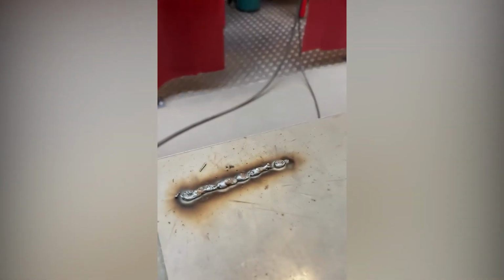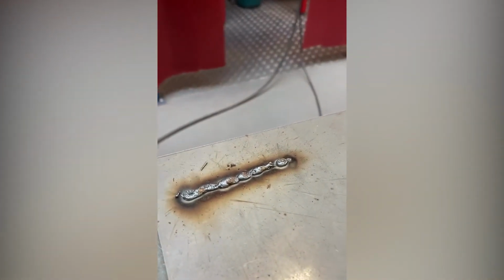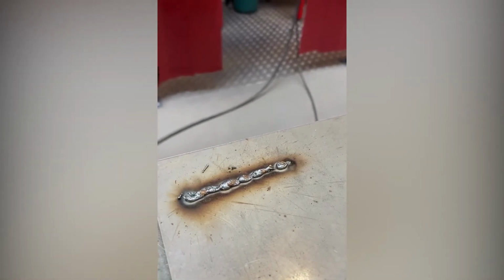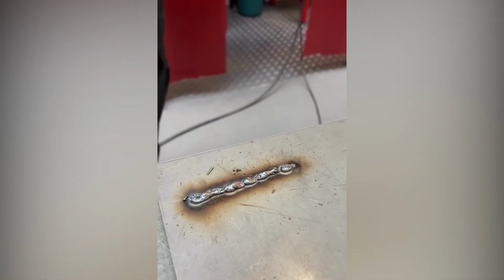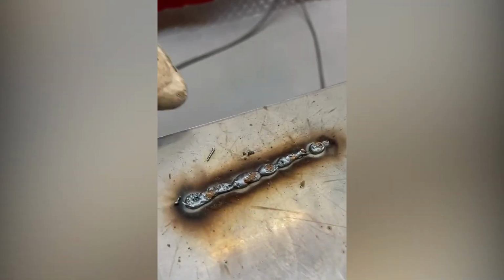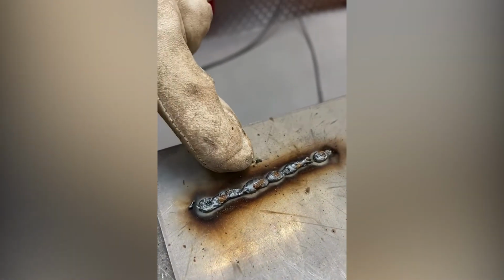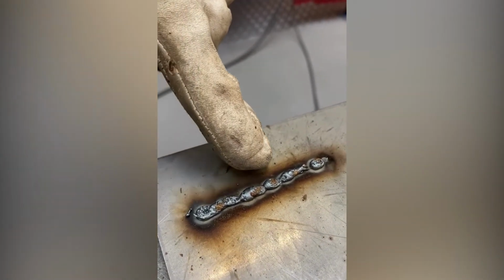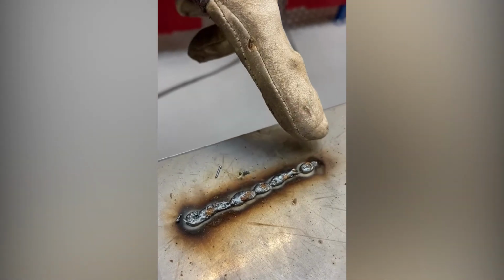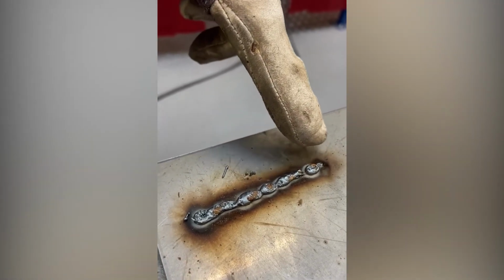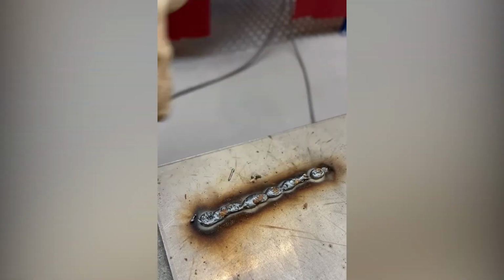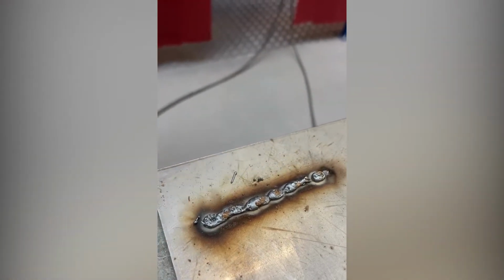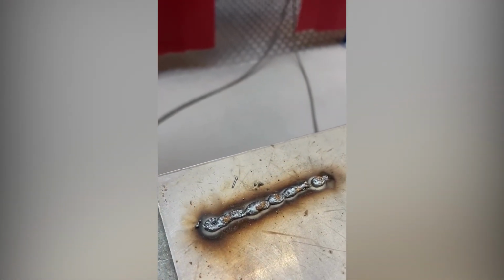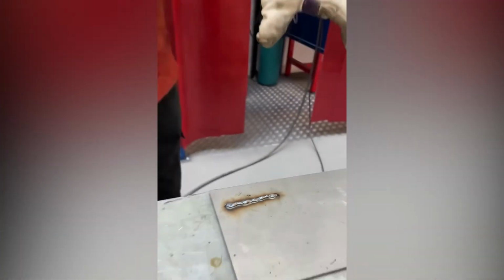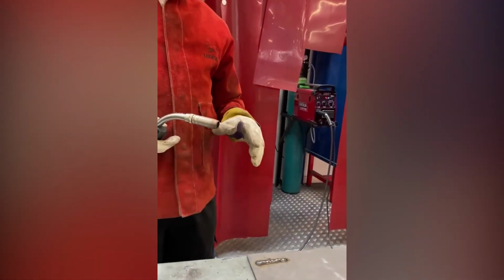That's the first weld without gas. It is very stop-starting, spattery, and if you look closely you can see there's a lot of what's called porosity, and that is because the air that we breathe has included all sorts of impurities into the weld. So when we use the shielding gas, that will blow the atmosphere away and leave a nice clean weld.